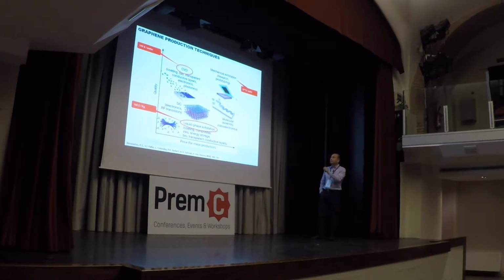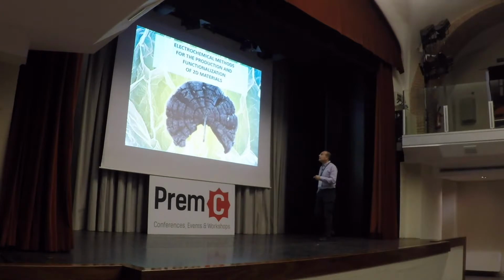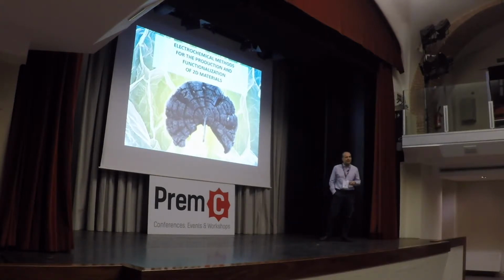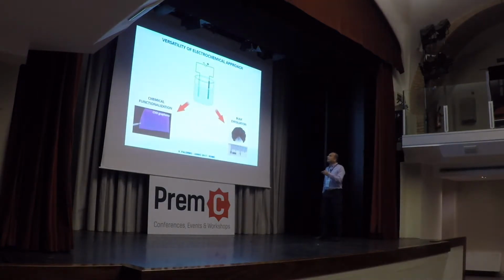But we can really produce and process it in lots of different ways. Even if it's really difficult still to have it processable as we want it in polymers, in composites, with the quality that we want. That's why since some years we are using a different approach using electrochemistry to process and functionalize this nice material. I will make some short examples of this. Basically, you take advantage that graphene is conductive, and actually graphite electrodes are used a lot also in electrochemistry, and use an electrochemical setup to enhance the reactivity of this otherwise chemically stable material.